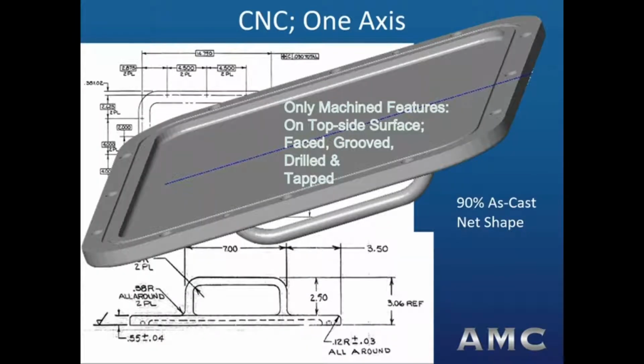This one is an actual DLA legacy casting with its 1977 2D drawing in the background. It is a 1 setup, 1 axis, vertical or horizontal CNC machining example. Shown in the foreground is the first solid model built by the mold cavity tooling builder, which replicates what the drawing calls for exactly. It does not have draft or parting lines or other features of its air-set sand casting process. This first solid model just replicates what's required on the 2D drawing. The casting is 90% as cast in its net shape, and the only machined features are on the top side surface, faced, grooved, drilled, and tapped.